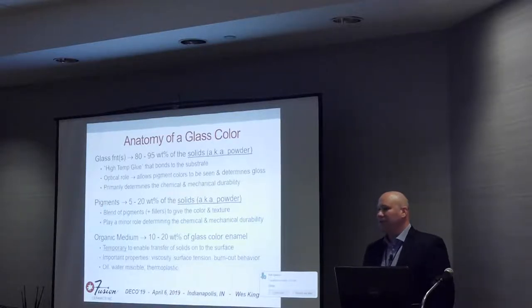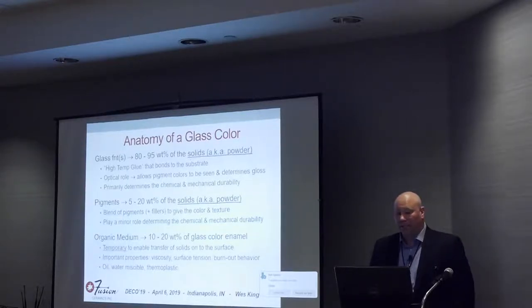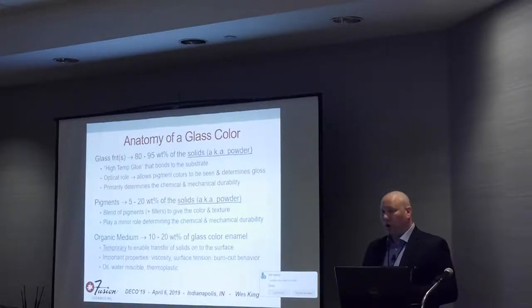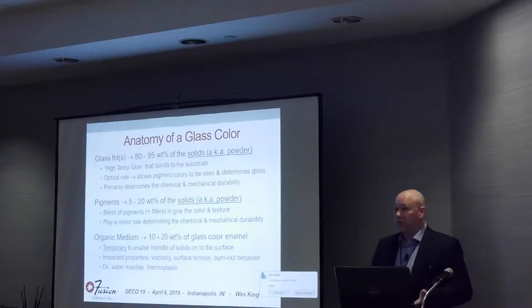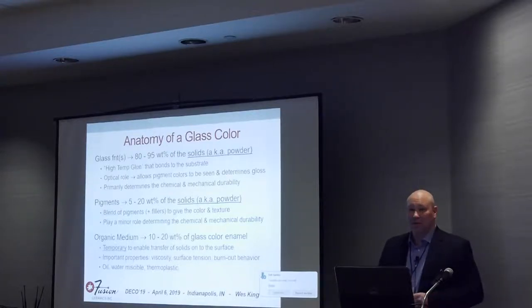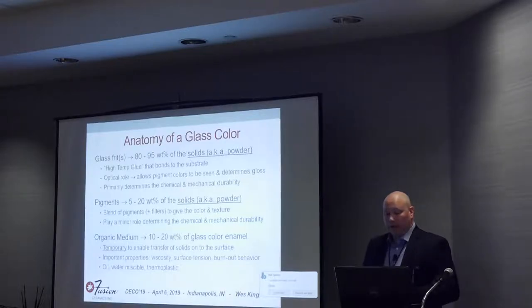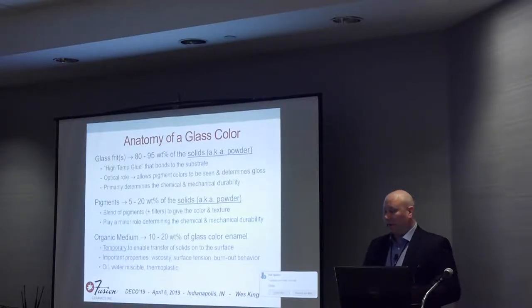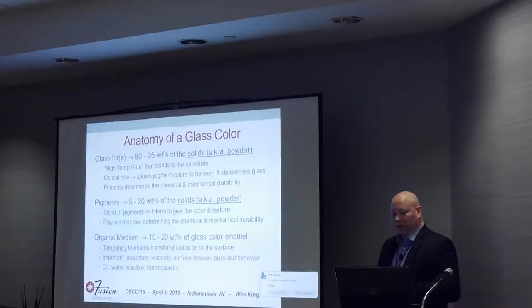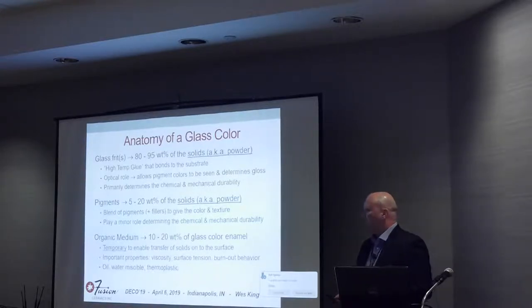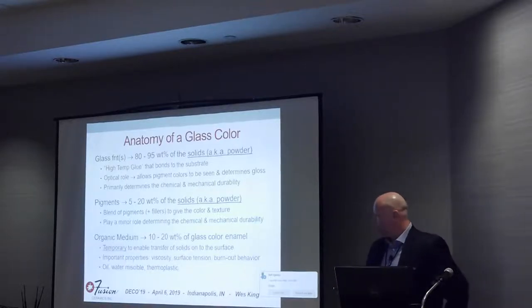The most important thing to point out is that the organic medium is temporary—it's going to be removed. That's a key part of a lot of the problems that come about during the process. It's very important for how you transfer the powders to the surface. Important properties include viscosity, surface tension, and burnout behavior. Typical mediums would be oil-based, or water-miscible based on alcoholic or other solvents, and then there's thermoplastic, which is more like a wax—some people describe it even as a crayon.